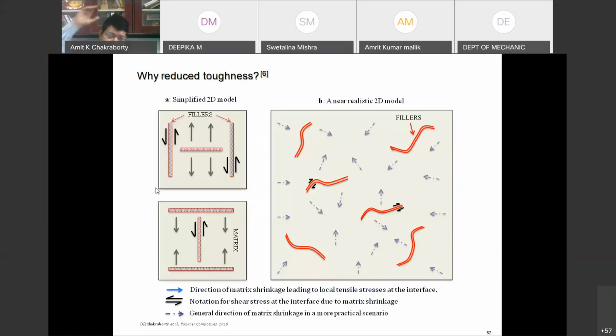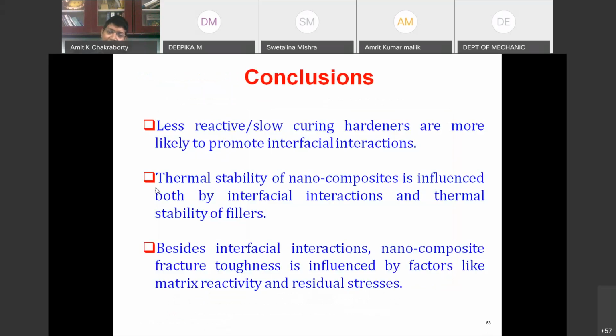So this slide basically shows that internal stress can be generated in opposite directions, which can oppose each other, as a result of which, even though we have improvement in the interfacial adhesion, you do not always translate this into the improvement of mechanical properties.